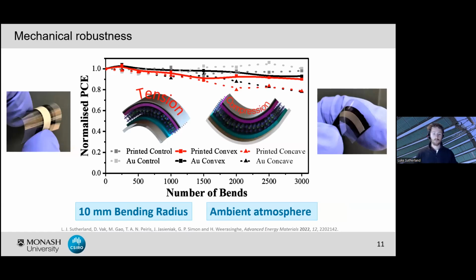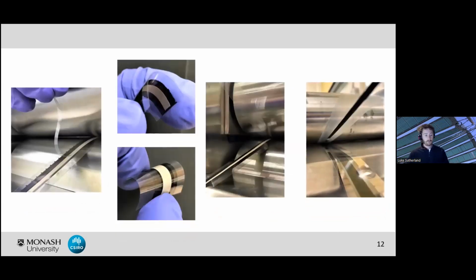However, again, once we compare to our evaporated gold, we see almost identical performance drop in these devices, which leads us to conclude that this isn't actually due to degradation of the electrode interface itself, and potentially is one of the other functional layers. And so within this work, we're able to demonstrate, again, some really promising results using this lamination technique.